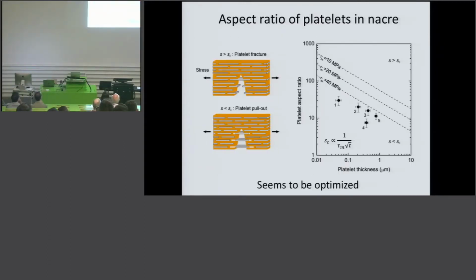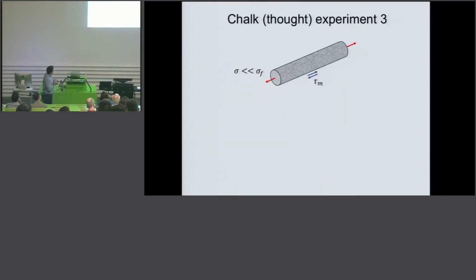And what you see is that indeed, there seems to be this correlation that the thinner the platelets are, the higher is their aspect ratio, indicating that indeed this seems to be a design principle of the seashells. All right, so the other experiment and the last one is the following.